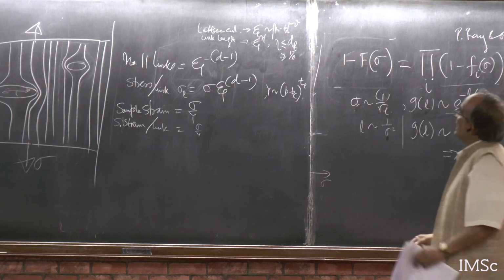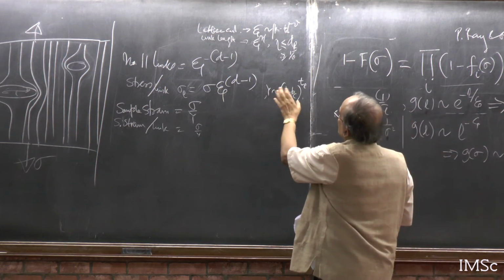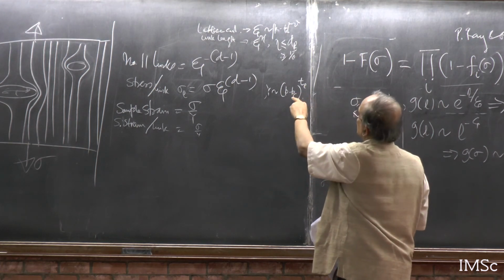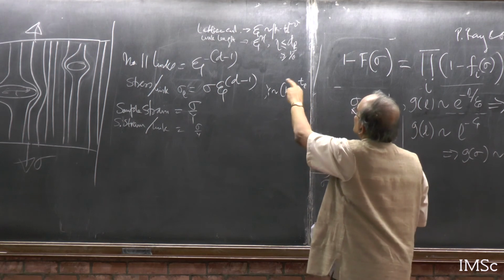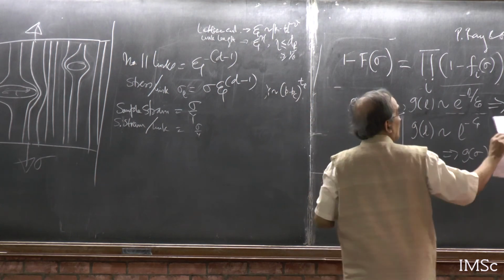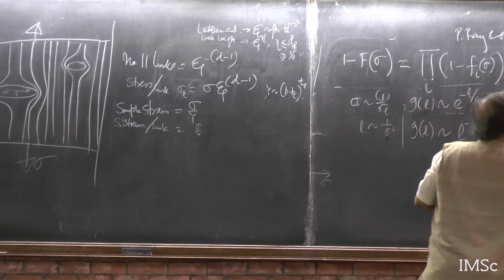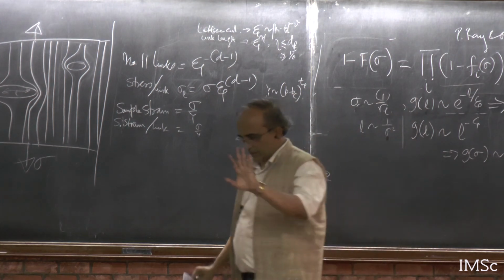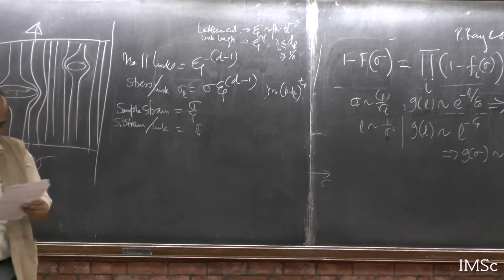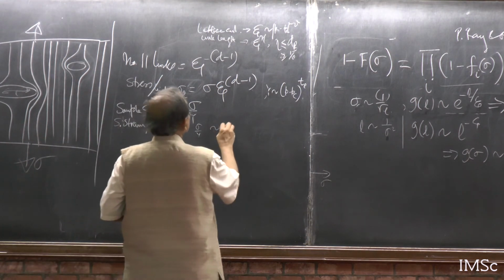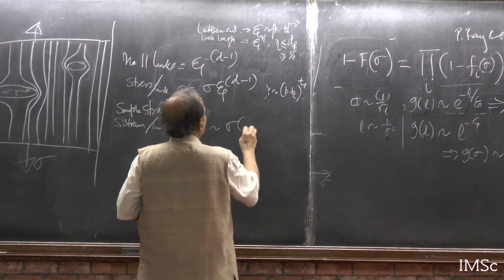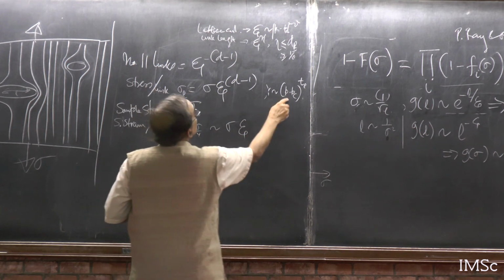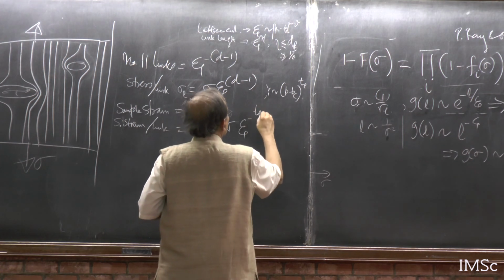As I said, this elastic or any linear response is a perfectly defined quantity as p goes to pc and volume goes to infinity. People have tried to find conductivity in a random resistor network, and how it grows near pc, and that exponent is a linear exponent known from percolation statistics. So let us write everything in terms of xi. Xi is p minus pc to the power minus nu, so t_e by nu.